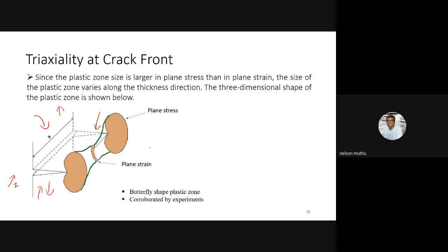So if you allow the crack to propagate for some time, initially you have this through thickness crack, and it will propagate initially like this. Because, as I said before, in the plane strain region, with a small plastic zone, it is propagating faster, and then it propagates like this. So gradually it will become tongue shaped. That is how it propagates. That is the effect of triaxiality. The triaxiality sort of powers the rate of crack propagation.